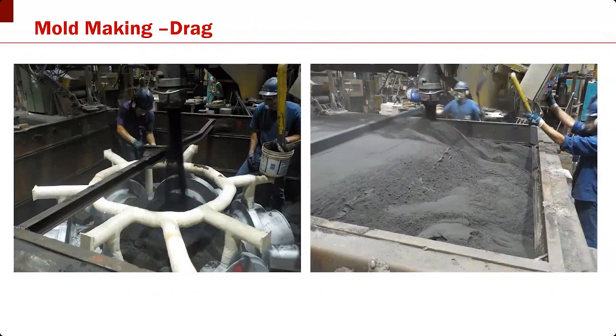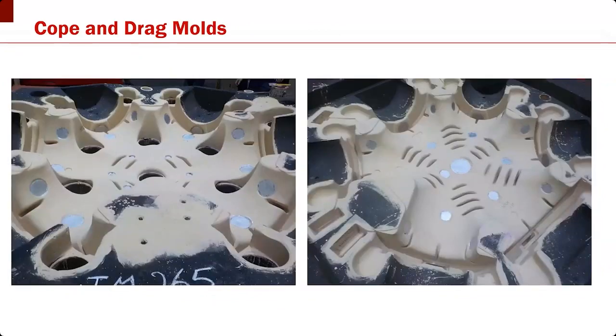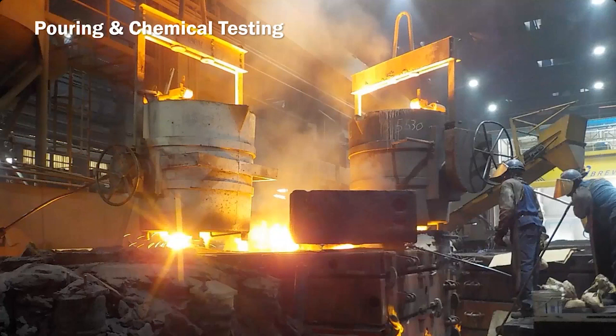That tooling is basically the negative and the positive of the part. And so we're surrounding it with chemically treated sand that sets up and has a binder and becomes very hard very quickly. And that will ultimately be what the molten metal is poured against. So here you're seeing the actual sand molds. The entire thing is enclosed in a steel box, basically to counteract the fluid pressure of the molten steel as it's poured into the mold.